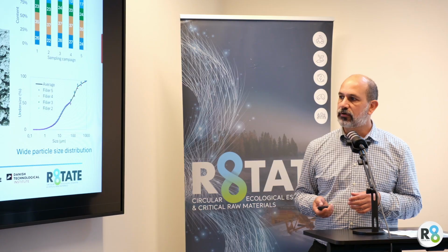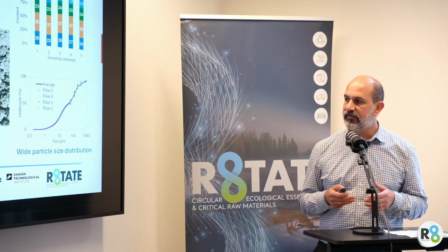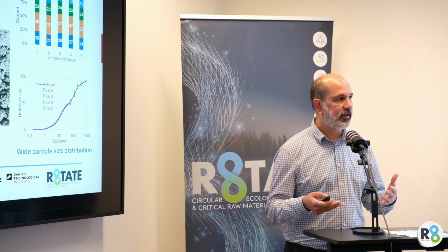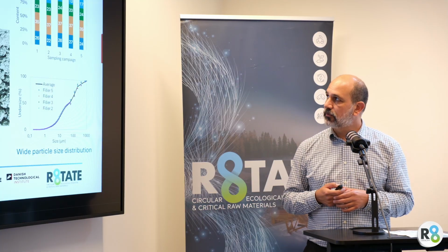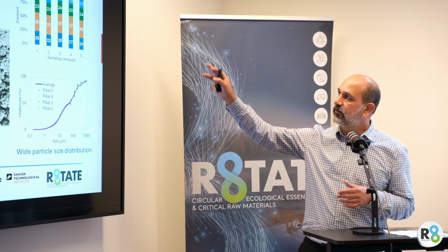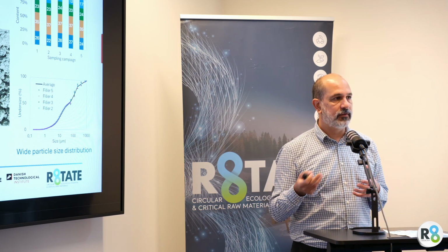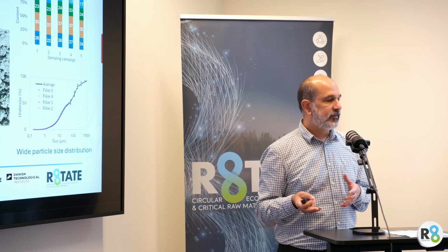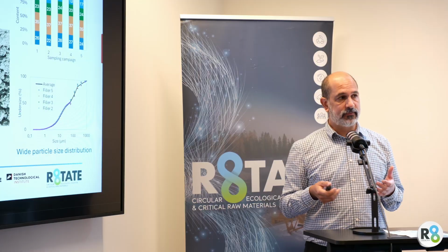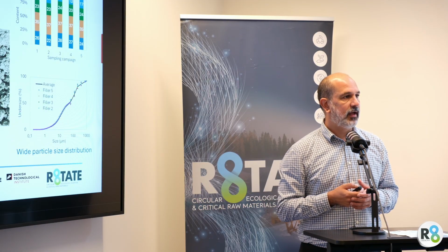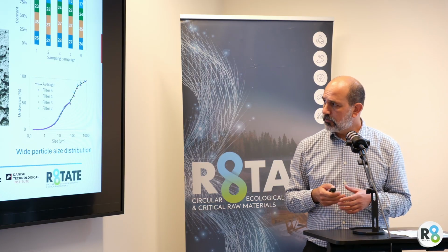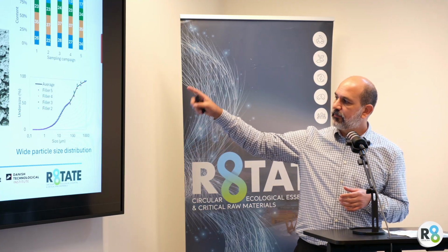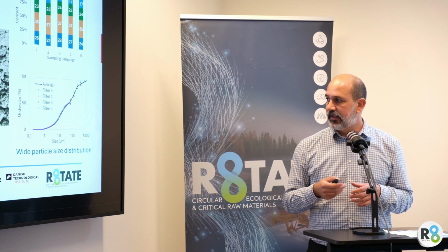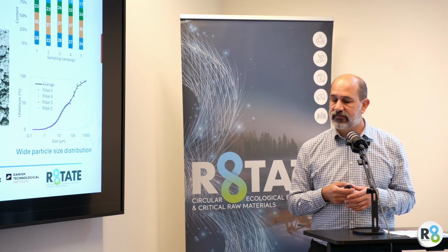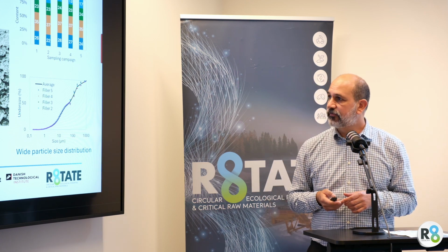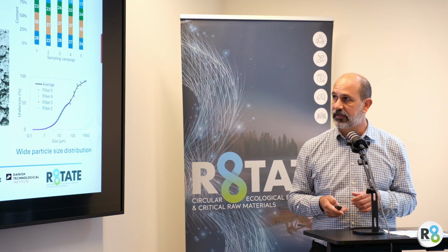So we work on the technical validation, mostly at Vito, but as I said, also the end-of-waste criteria to facilitate the implementation of these technologies and the demonstration with pilot production. We analyze the material and we determine that it contains approximately 25 to 30% of clay material. And this is quite significant data because it explains a little bit the value it can have for producing construction materials. I will go over the technologies in a minute. We also determine with different sampling campaigns the wide particle size distribution that we have in this material, also requiring some mechanical treatment for the applications.